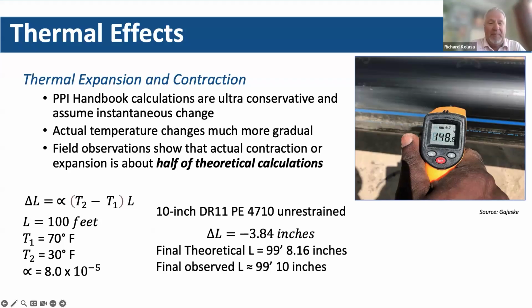So it can absolutely reduce your stresses on those type of situations if you had those thermodynamic differences, right? Again, thermal expansion and contraction, one of the biggest areas that we're working on. We haven't really studied in the industry all the effects of the soil types that add load onto this pipe and what those frictional resistances are on the pipe to maybe increase or reduce or eliminate stresses as they occur. But in this particular calculation, this is an unrestrained calculation that gives you an idea of what the worst case scenario would be for 100 feet of pipe and a 40-degree difference in temperature with the expansion and contraction value that we have. You're looking at, in that 100 feet of 10-inch DR11, 3.84 inches of expansion or contraction, depending on which direction you went. As you went cold, it'll be negative. As you went hot, it'll be positive. But that's not really a real concern. We just need to understand it because there's some stresses if you had a system that is above ground and you had some stresses that are applied with that expansion or contraction.